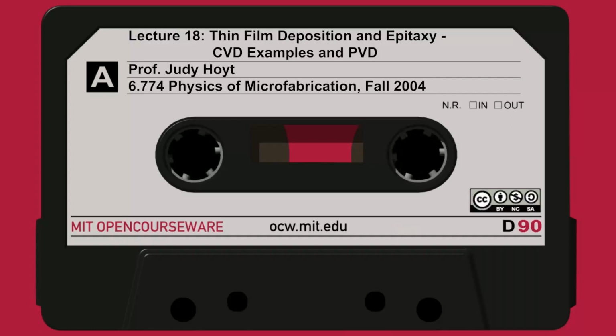The third one down is the undoped film. So if you take film A here and heat treat it, so you anneal it afterwards at 1,000 degrees, you can see the grains are still columnar, but they've grown. See, the average grain size looks larger. It's a little bit hard to tell an average grain size in cross-section, but you get that impression. But look what has happened to the surface.